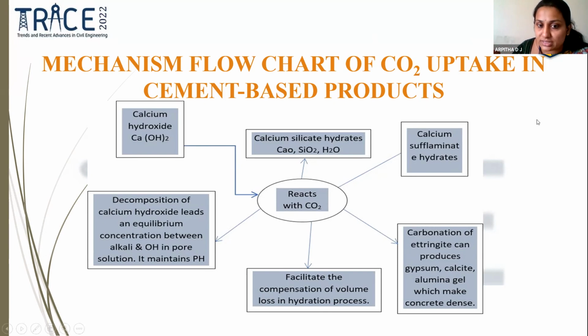When calcium hydroxide reacts with the carbon dioxide induced in the concrete, the decomposition of calcium hydroxide leads to an equilibrium concentration that maintains the pH and OH in the pore solution. Definitely it attains pH maintenance, which facilitates compensation of volume loss in the hydration process, and also the ettringite formation at the ITZ section. The ettringite produces gypsum, calcite, and alumina gel.